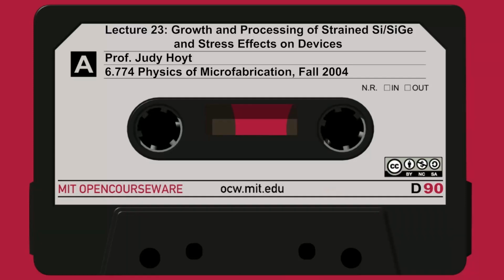Silicon germanium has a larger lattice parameter than silicon. Pure germanium is about 4% bigger. So this 30% layer is going to be a little bit larger in its lattice parameter. So if it's relaxed, it's bigger. And if the silicon layer is thin, when you grow it epitaxially, the silicon lattice will actually stretch in the X and the Y directions to match that of the substrate. As long as it's thin enough, it's energetically favorable to stretch the bonds instead of breaking them. So this silicon is stretched.